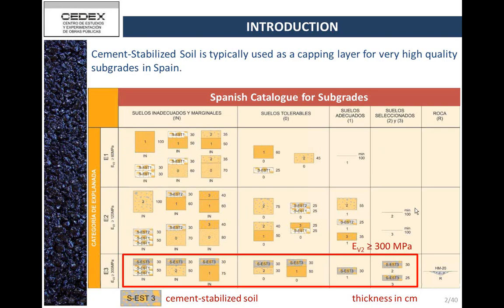E2 is a medium high quality subgrade, and then E3 is a very high quality subgrade. That's a real good subgrade. All of these subgrades have a cement stabilized soil layer on the top. This could be like the capping layer of the subgrade. And almost always we use 30 centimeters, which is like 12 inches. So the study we are conducting is just to study this material. I should say that on top of these subgrades, we always require a bearing plate modulus of 300 megapascal, which is a really high value compared to a conventional soil.